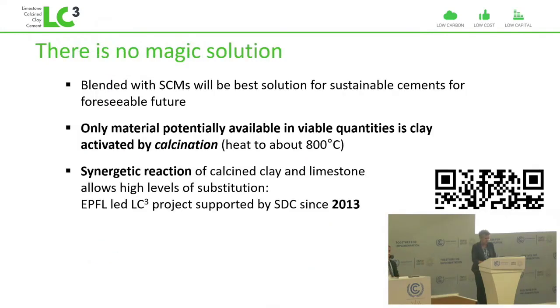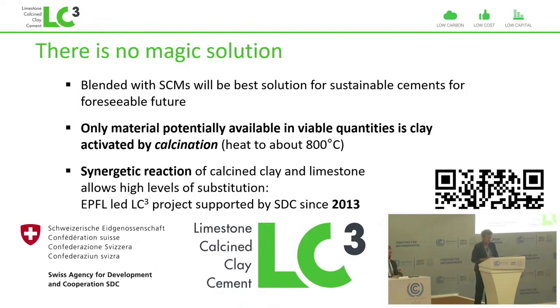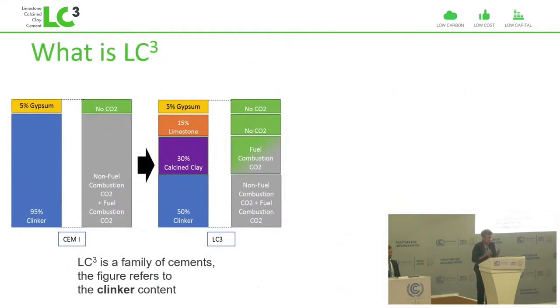So this is what led us to the idea of what we call LC3, that to realize that this strategy of substitution was the best strategy because it can be done by everybody, it can be scaled, it can be developed very, very fast, but the only material available in the quantities we need to expand this technology is calcined clay. And then we realized that if we combined calcined clay together with limestone, we actually got a synergetic reaction which allowed us to go to even higher levels of substitution. So this is the idea of LC3.